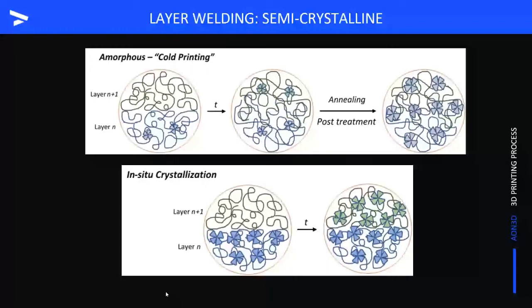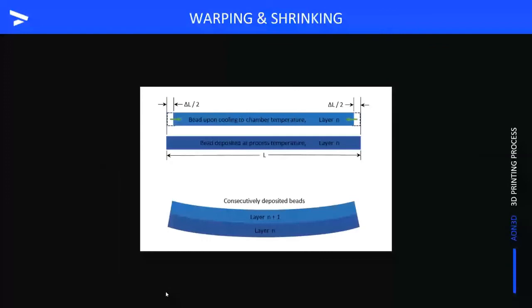Thermoplastics typically decrease in volume as they cool from molten to solid states. The environmental temperature, including the chamber and bed temperatures, have major impacts on how much the first layer shrinks as it is deposited. Each following layer that's deposited on a part will also go through the same cooling and shrinking process, creating residual stress that exists within the part and accumulates layer by layer. When the incremental stress that accumulates is large enough to exceed the attachment force to the bed or even the interlayer bond strength, the part will warp. Usually, this results in the edges of the part bending outwards, although it can show up in other ways as well.